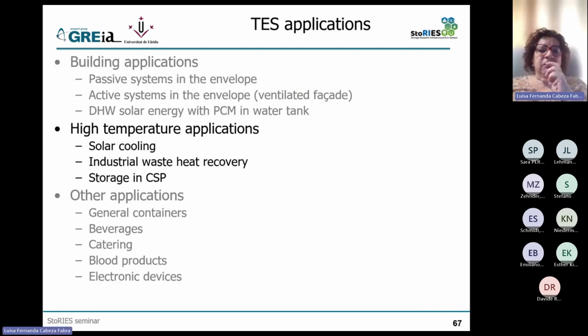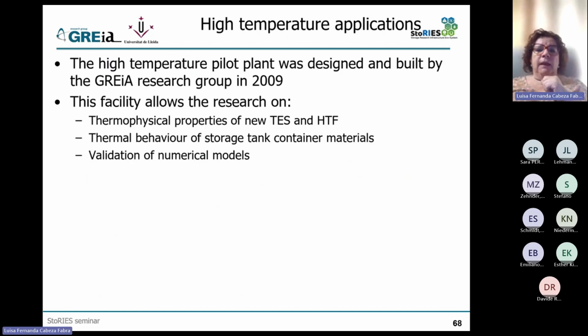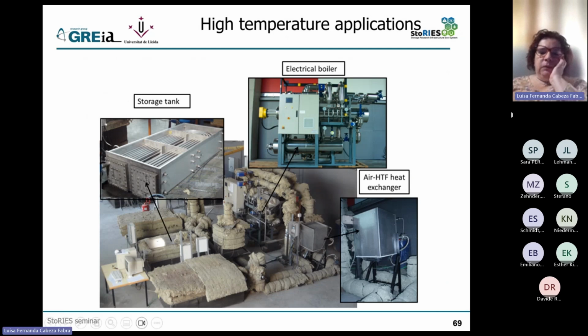Okay, high temperature applications. There are some examples here. One is this pilot plant that we built in Lleida, also University of Lleida, in 2009. And the idea here was to go to higher temperatures, but also to higher sizes, okay? And, okay, I will go into more details later, but this is the pilot plant. You see the image in the back where we have a storage tank. Our storage tanks were for PCMs around 100 kilograms of PCM, and we also had 2 molten salts tanks with 1 ton of